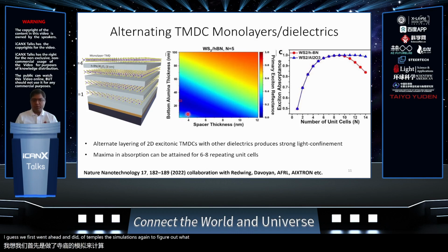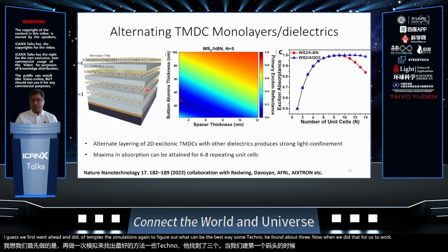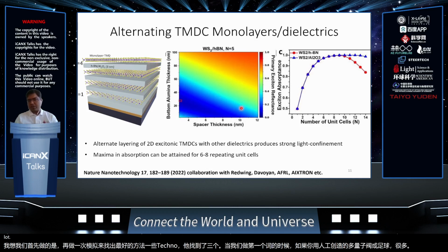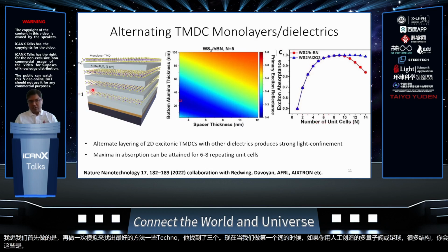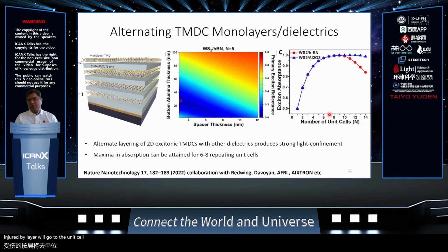Okay, so we first went ahead and did simple transfer matrix simulations again to figure out what would be the best spacer thickness. We found about 3 nanometers or so should work. And if you were to then artificially create this multi-quantum well or superlattice structure, you would see that even for thicknesses or number of unit cells, and each bilayer over here is a unit cell, for about 6 or 7 unit cells, you can get nearly 100% absorption.